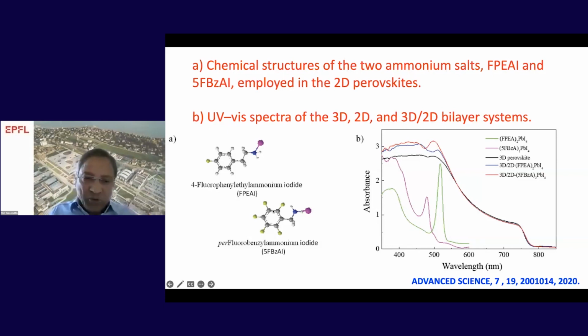Now, by making these two cations, you can form a two-dimensional perovskite. The two-dimensional perovskite absorption spectra is shown here. This is the fluorophenylethylamine absorption spectra of the two-dimensional perovskite. This is the pentafluorobenzylamine cation containing two-dimensional perovskite. Now, when we deposit this two-dimensional perovskite on top of three-dimensional perovskite, you can see the black line is the reference sample, pure three-dimensional perovskite. The blue is the fluorophenylethylamine two-dimensional perovskite on top of three-dimensional perovskite. And the red curve is pentafluoro two-dimensional perovskite on top of three-dimensional perovskite.